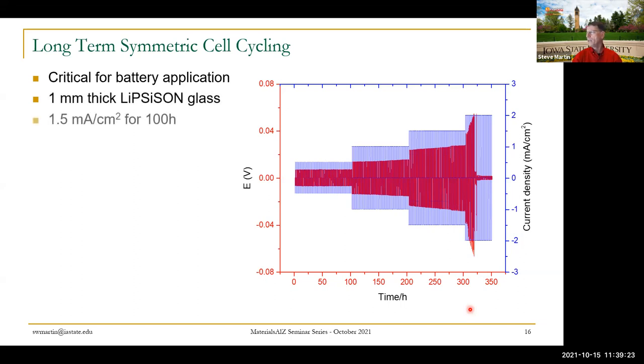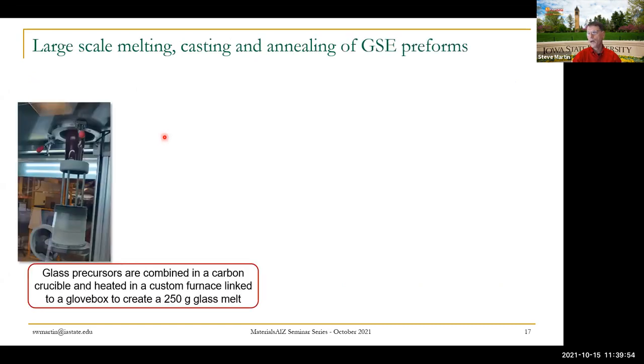Okay, just to show you that, of course, you don't want to run your battery for just an hour or a couple hours. You want to run it for many hundreds of days, if not years. And that's shown here, that we can cycle in this milliamp range for hundreds of hours. But when we kick it above 1.8 or 2 milliamps, it'll cycle for a little while and it'll short out eventually. We can run in this 1.5 milliamp range for hundreds of hours. This is a thick film glass. I haven't got to the thin film stuff yet, but this is a thick film glass, meaning we have pretty good stability. This is for the LiPSiSON composition.